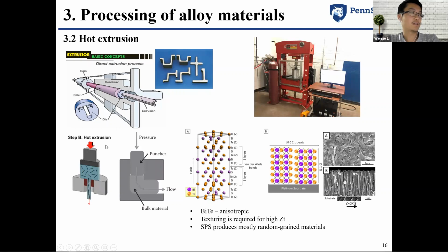What we are more interested in is using this hot extrusion method to texture certain types of thermoelectric materials. One example is bismuth telluride, which has a trigonal structure, not a cubic one. So it shows anisotropic thermoelectric properties in plane and out of plane. So texturing is really required to improve the ZT. SPS generally just produces mostly random-grained materials, as shown in this figure, but through hot extrusion we can get very well textured materials.